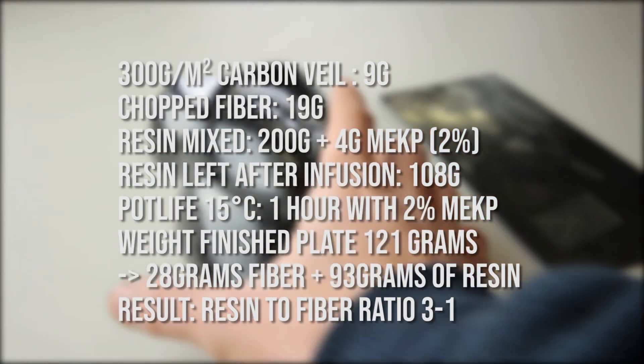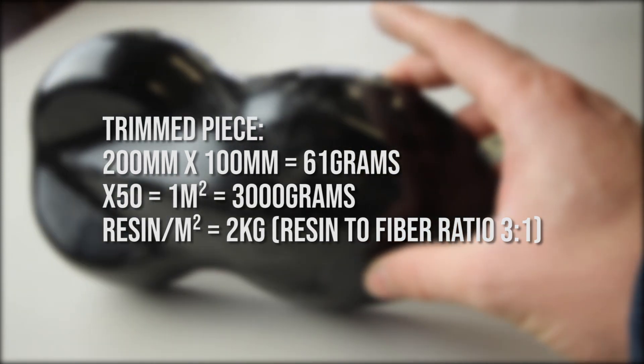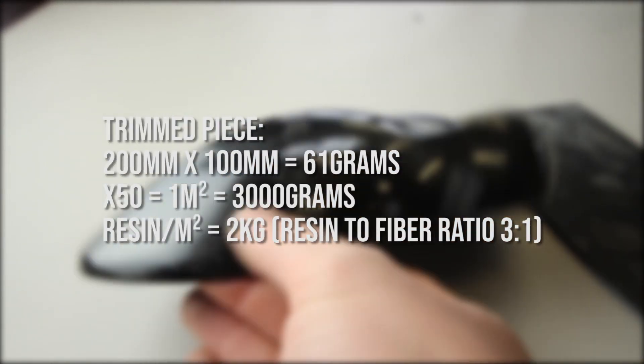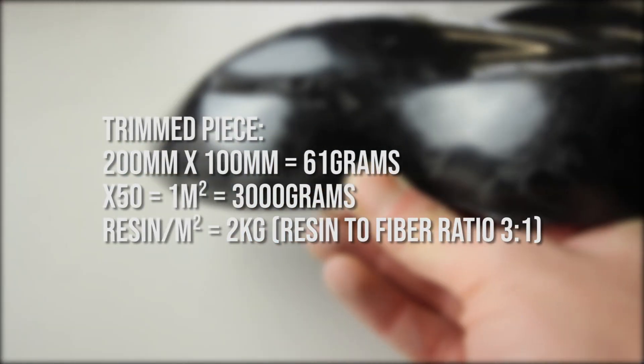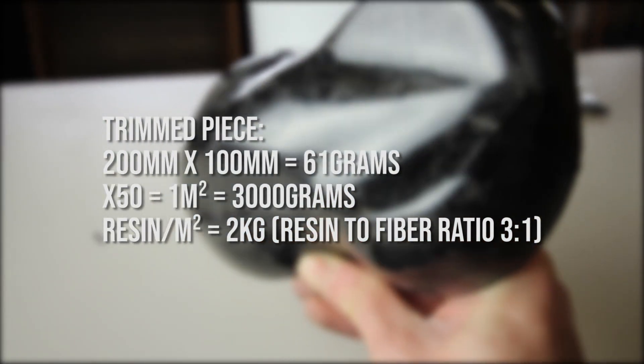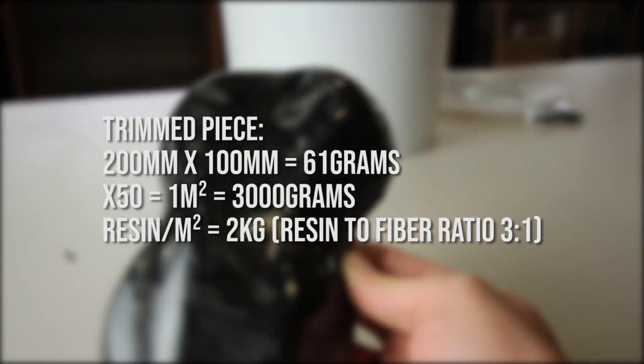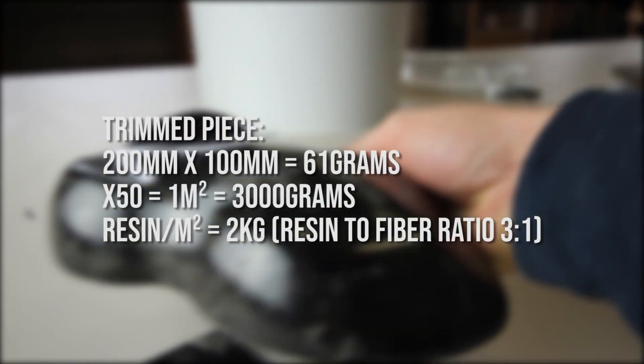Here you can see the results. I've used 28 grams of fiber - you can pause the video if you want - but the big conclusion is that you have a resin to fiber ratio of 3 to 1. So this is a lot. The veil takes up a lot of resin and you get up to about 2 kilograms of resin needed for one square meter. If you like this video, don't forget to leave a thumbs up. Ask for leave a comment if you have more questions and see you guys in the next one. Thanks for watching.